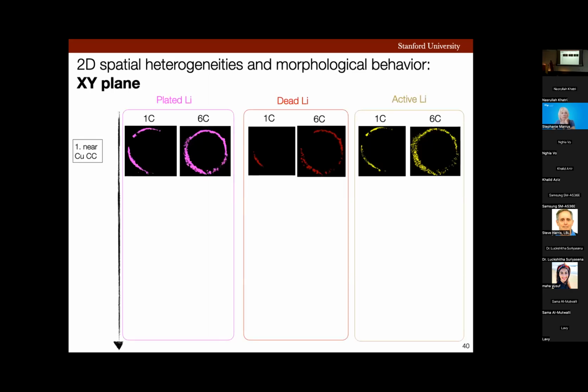Now first, near the current collector, we can see that at 6C, we have a lot of plated lithium as compared to 1C. Same is true for dead lithium. You would also notice that the regions that formed most plated lithium are the ones that formed more dead lithium. Regions that formed less plated lithium are the ones that formed less dead lithium. So this shows spatial heterogeneity in the formation of plated lithium in all the X, Y, and Z dimensions.